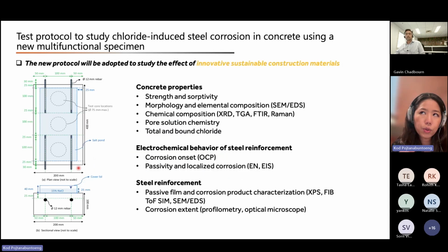To validate the model we developed, we come to the experimental part now. To validate the model, we have to have something to verify it. So in this case, we developed a test protocol, which is a sample that enables us to look at the corrosion of the reinforced bar from the electrochemical side, using electrochemical impedance spectroscopy or electrochemical noise. This is a rebar. There are 4 rebars. The dimensions are given in the photos.